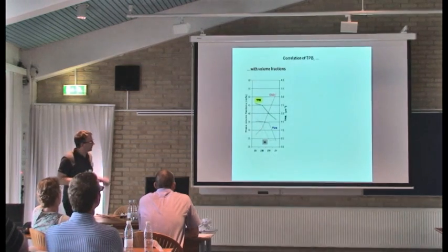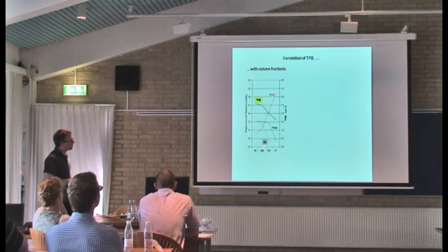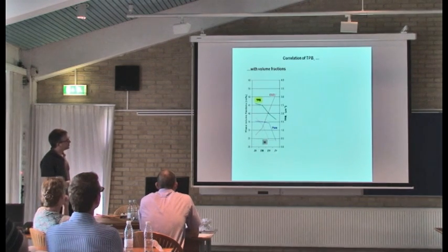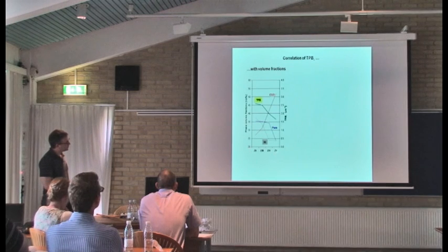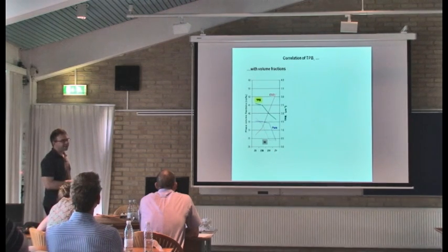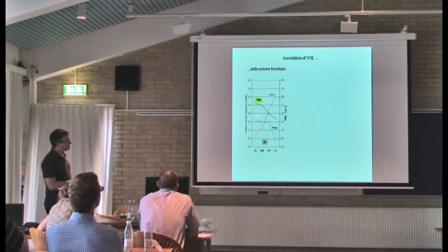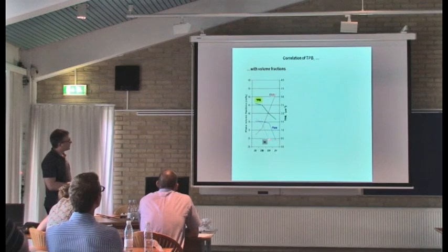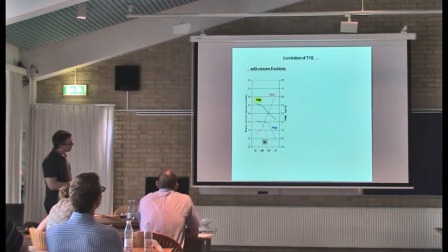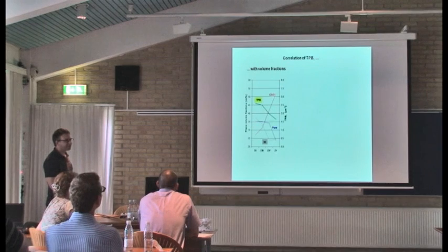So we can also measure the TPB in these graded microstructures, looking at how TPB changes with volume fraction. It's actually a complicated pattern. Most probably it's strongly correlated to the most coarse phase, the nickel, but as we change the volume fraction of nickel, we also change the particle size.